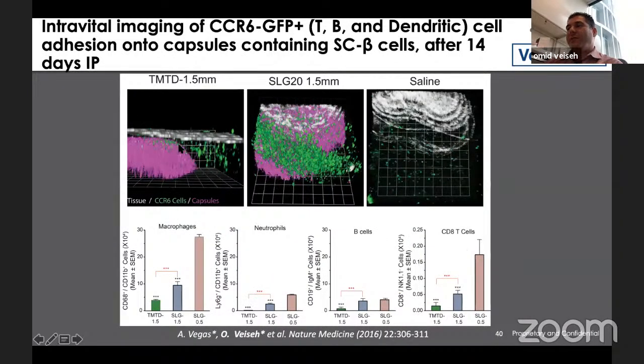And then we profiled the immune response to these capsules, and these also had the cells in there. This was a xeno model where you have human cells inside of these immunomodulatory coatings. What we noticed is that the modification suppresses the macrophages and the neutrophils, which are involved in the foreign body response. So that was expected. But the other thing that we noticed is that they actually suppress the activity of the cytotoxic T cells and the B cells. And this is important because these cells could secrete molecules that could be detrimental to our encapsulated cells. But because we're reducing the overall inflammation and fibrosis, those cells are also not activated as much either.